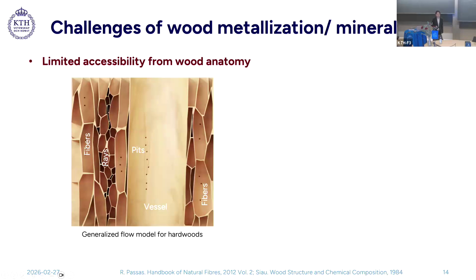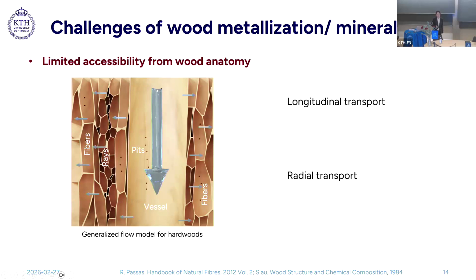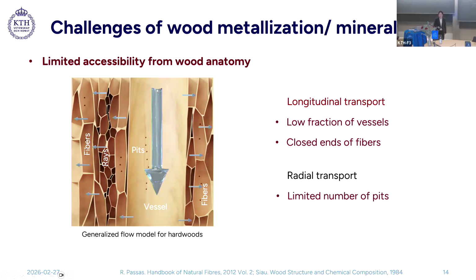From the flow model in hardwood, we can find that the longitudinal transport is dominated by vessels. Tangential and radial transport is enabled by pits, which create interconnected pathways between cells. However, take balsa wood as an example, which is a main wood species used in this thesis. Although vessels facilitate longitudinal transport, they have a very low fraction. The dominant cell type in balsa, which is fibers, feature a length of 0.2 to 1.2 millimeter and closed ends, severely restricting longitudinal transport in thick samples. Besides, the number of pits is rather limited. Pits are also susceptible to blockage by newly formed particles, making the uniform metallization or mineralization difficult.